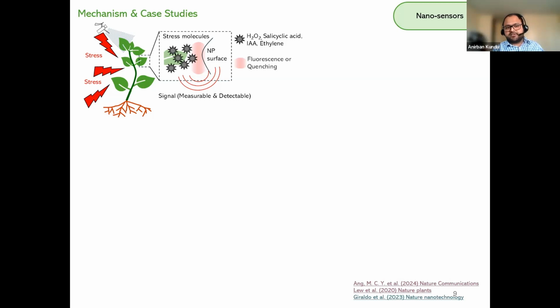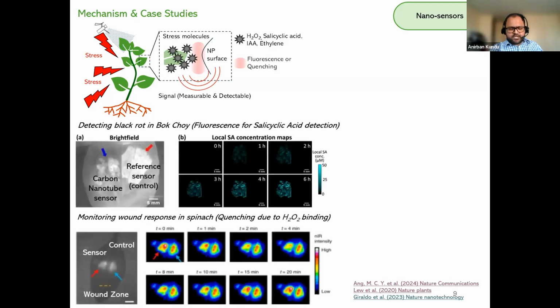So what people have done in the literature is they have prepared nanoparticles that respond to the presence of these stresses using a sort of fluorescence or quenching. So you have a nanoparticle, it has a receptor that on identifying the stress molecule either gives out a fluorescence, or if it already has fluorescence, it is quenched. So you can use that signal to identify when the plant is in stress and when it's not, and you can monitor the stress over time. And this signal is measurable or detectable. Think of near-infrared NIR radiation, or think of Raman spectroscopy that can help you measure and detect this signal over time. A number of fantastic studies over here, and going to the first one.